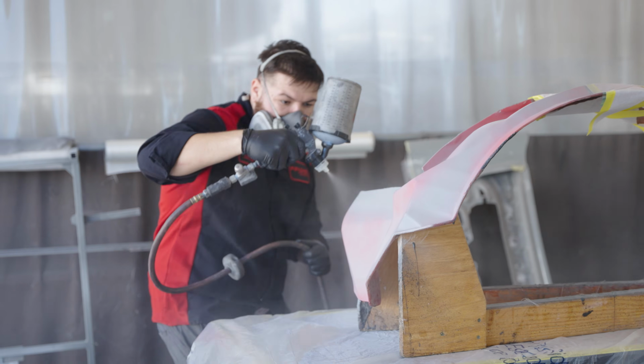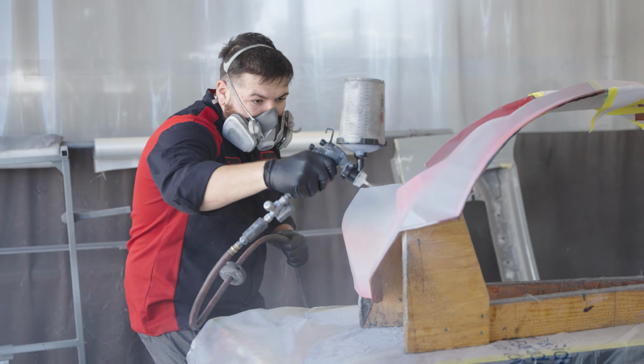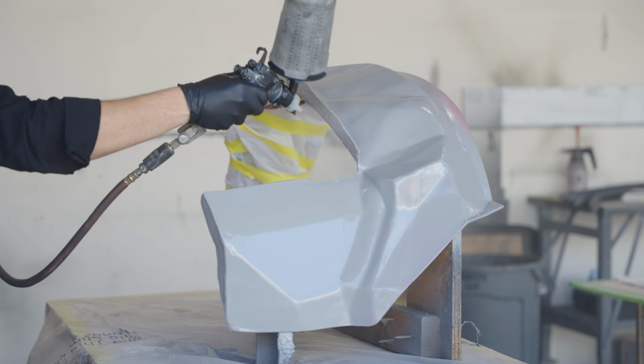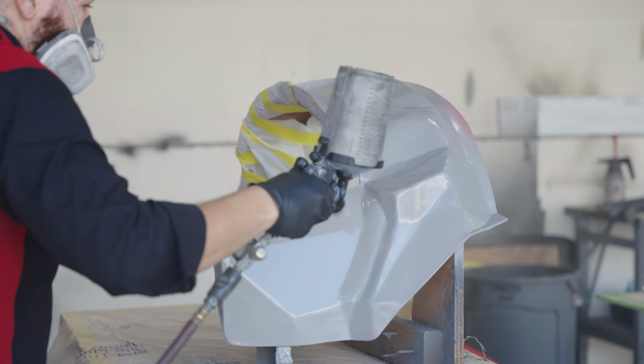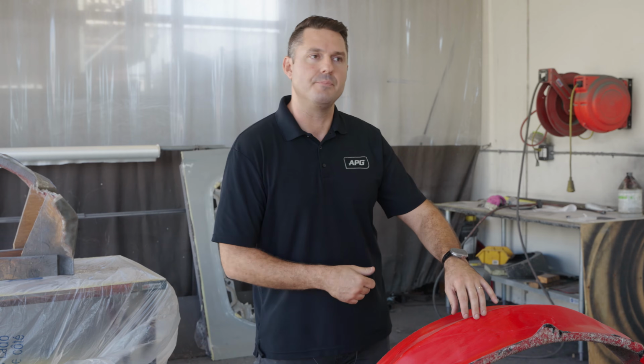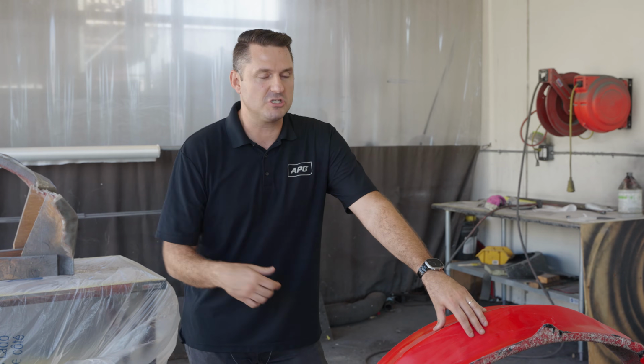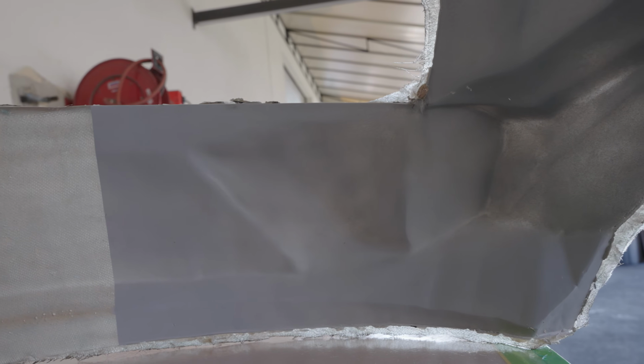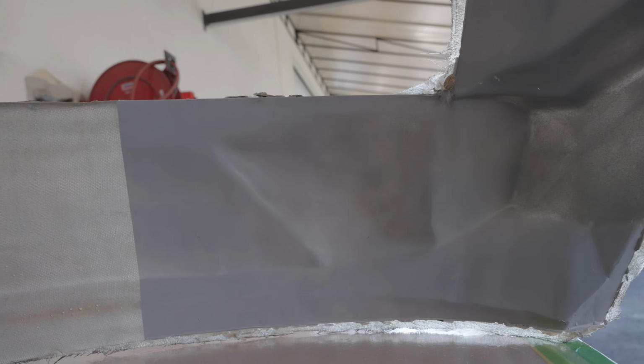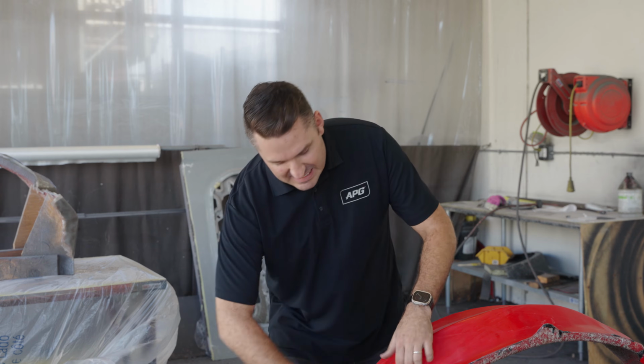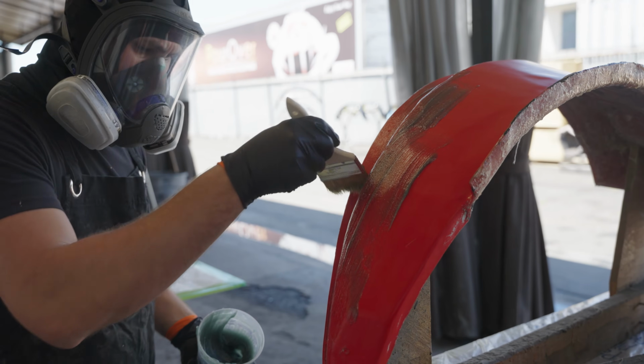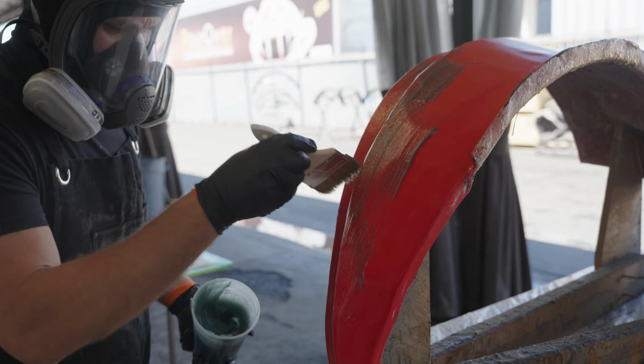So, how are we gonna make this part? Step one, heavily gel coat your product to create that perfect contour and that perfect first layer against your mold surface. And that is a critical point that we really wanna get into. They are not spraying in a primer, they're spraying in a gel coat. They are spraying in a gel coat because they wanna create a perfect appearing product. Step two, you're gonna grab some of your slurry mix and you're gonna start filling some of the sharp corners, peaks and valleys to kind of flood that in. You're gonna create that secondary layer on top of the surface coat, and then you're gonna start laminating your fiberglass.